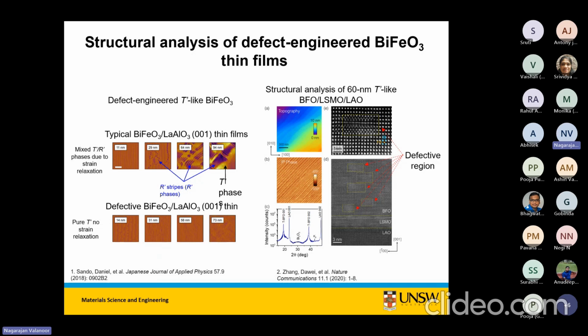Actually, those guys even at 5 nanometers, they're getting what's called mixed phase. And this is the classic thing that happens in most chambers. I think Sujit's chamber, Pawan's chamber, everybody else's chamber will show this, I can tell you. You grow and you start to see the small specks. This is the mixed phase, the R phase nucleating, and eventually you will have this really well-defined striation, which is basically this system has got R and T phase, rhombohedral and tetragonal.